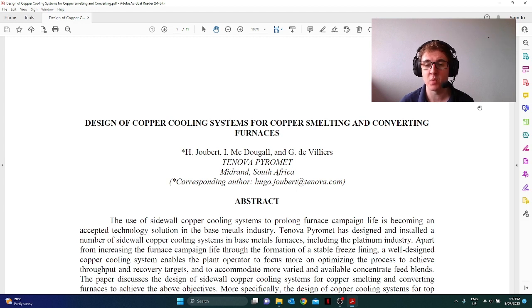This particular paper is one of those really interesting ones that you sometimes see people doing in industry. So it's a bit of a story here. A lot of smelting furnaces have multiple parts to the lining system itself. First, the molten bath is contained by a refractory or a freeze lining system. Then you have a binding or a steel shell system. Depending on the furnace, they're either completely refractory, a mix of refractory and copper cooling systems or other cooling systems, or complete cooling systems, and they always have a steel binding system.